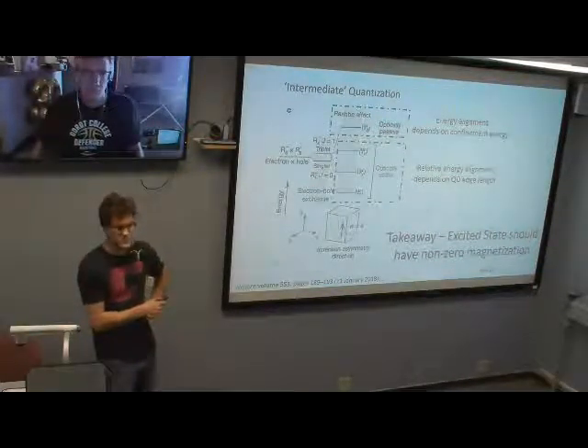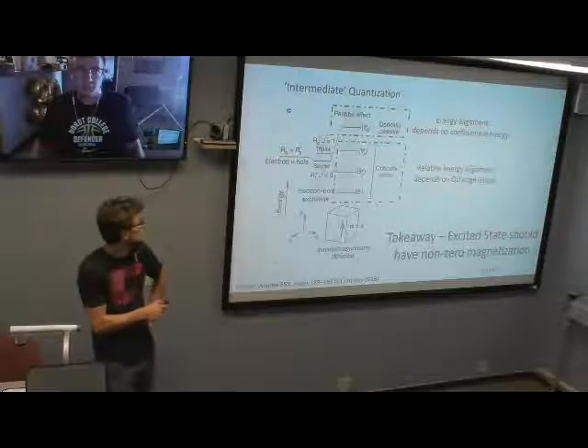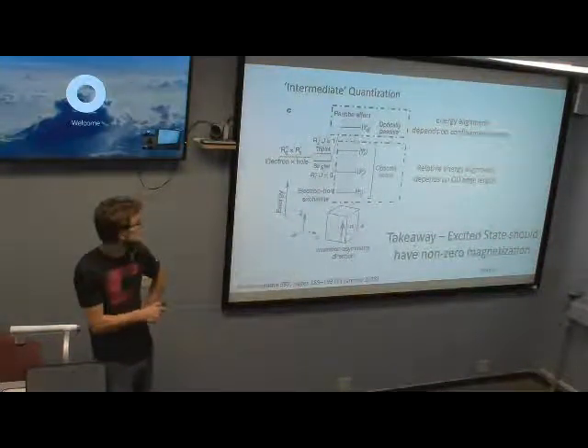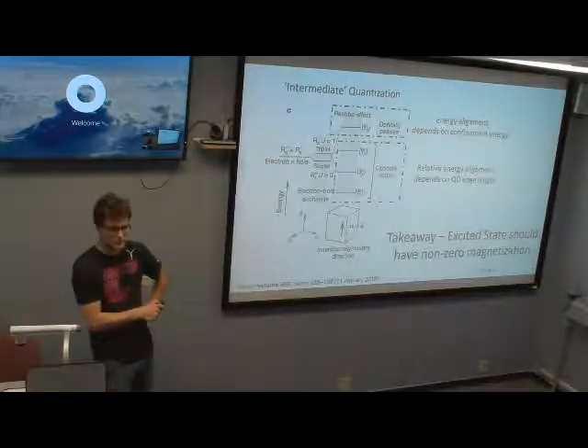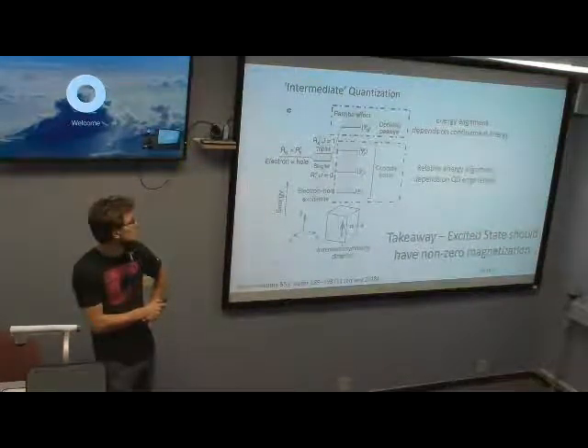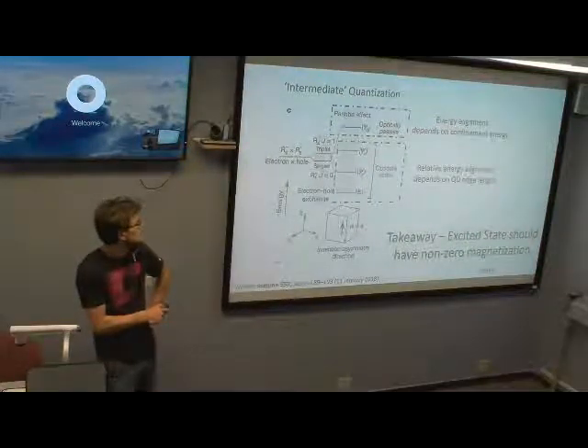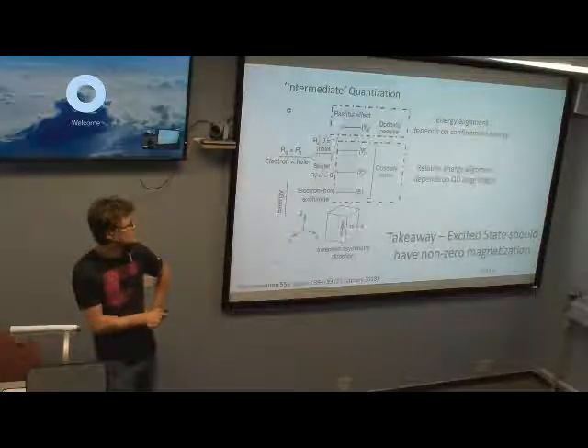If you include the Rashba effect for these perovskite quantum dots. If you just included confinement, which is this step here, your singlet is lower than your triplet. But then, in their calculations anyway, when they included it, the singlet increased and the triplets split.